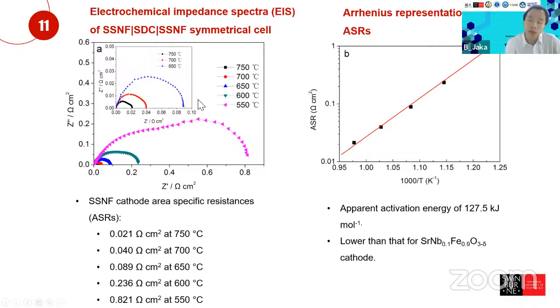And the next one shows the characterizations of the symmetrical cells for the different cathodes. Okay, so in here you can see that as the temperature is increased, the semicircle arc size becomes smaller. This one is at 650, this one is at 700 and 750. Because when you increase the temperature, you are making the diffusion process for the ions and the electrons much easier. As a result, you reduce the resistance of the cathode. And as you can see, if you decrease the temperature lower than 650, to 600 degrees Celsius and 550 degrees Celsius, the arc size becomes higher.